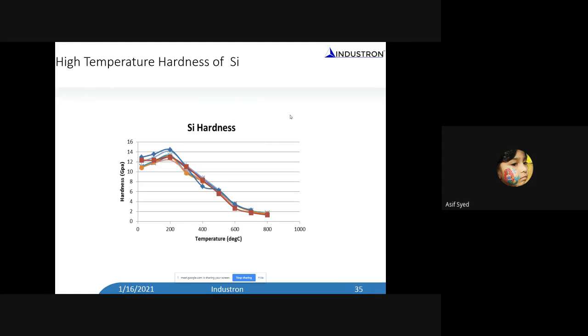So this is something that I wanted to give as we did very recently. This is an experiment that we did on silicon, and this is done as a function of temperature. Normally when you increase the temperature of the material, you should see a decrease in strength, and that's because mobility increases and dislocations can move easily. That's what you expect. The hardness or the yield strength will decrease with increasing temperature.